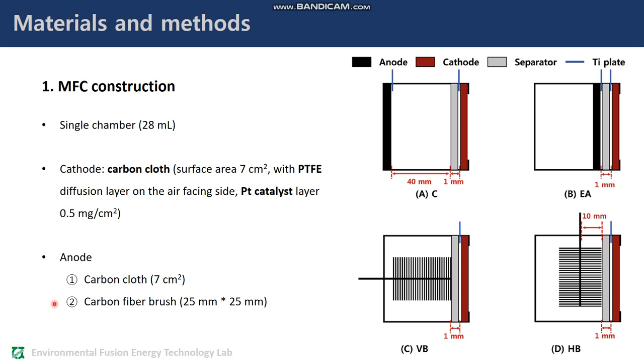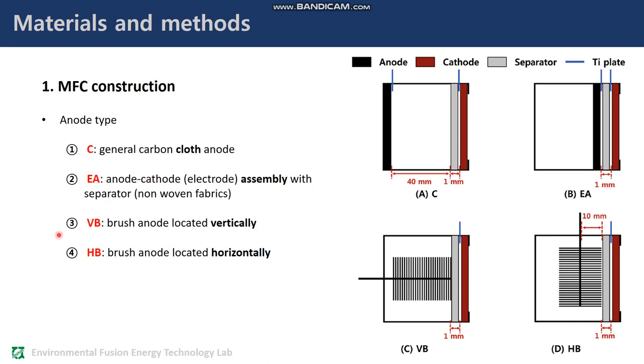Two anode materials were used in this study. First one, carbon cloth was used as an anode. The second one, brush anodes were made from carbon fibers twisted between 2 titanium wires. Before inoculation, they were heat-treated at 450 degrees Celsius for 30 minutes in a digital muffle furnace. To compare the difference in performance by anode structures and materials, 4 anode types were tested.